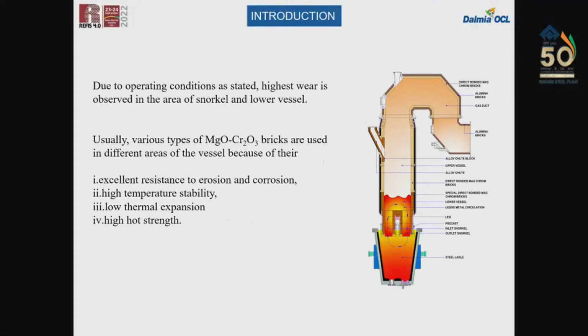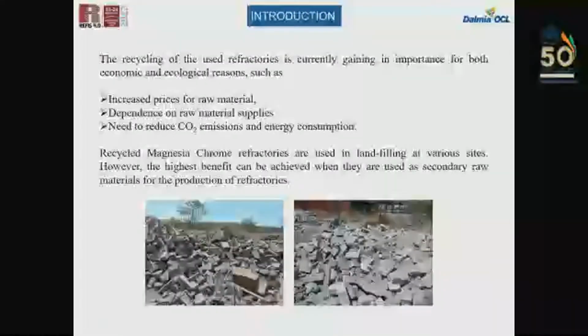So in the RH degasser, due to all the conditions which we have stated above, the best bricks now being used are magnesia chrome bricks. This is used mainly because of its very excellent resistance to corrosion and erosion, high temperature stability, low thermal expansion, and very high hot strength.